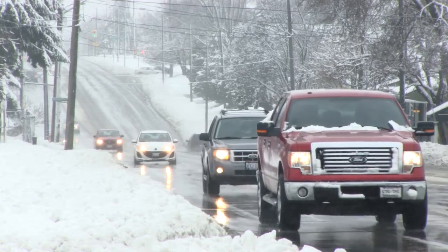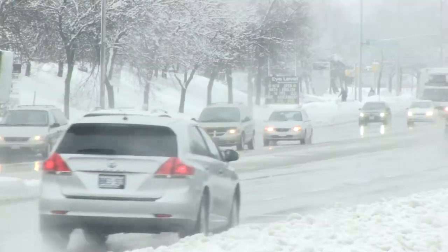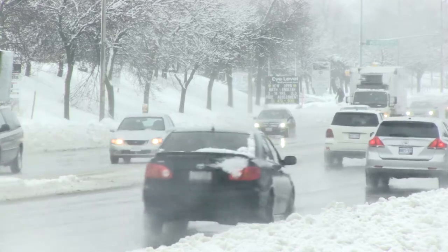Partly because of the environment, when we drive cars along the roads in the northern part of North America, of course there's salt on the road, which is put there to de-ice the roads. And salt contains chloride ions. Chloride ions are nature's agent for breaking down the phenomenon called passivity, which protects the metal, and returning the metal to its oxidized state. So it's the chloride ion which is the bad actor, and that's ubiquitous — it's everywhere. In fact, they put it by the truckload on the road.